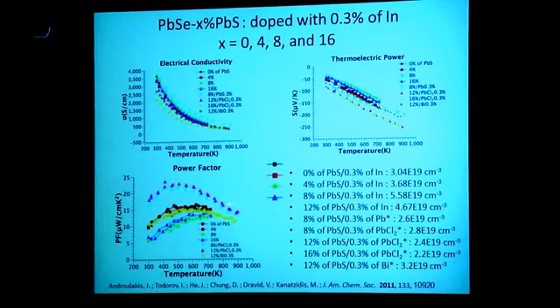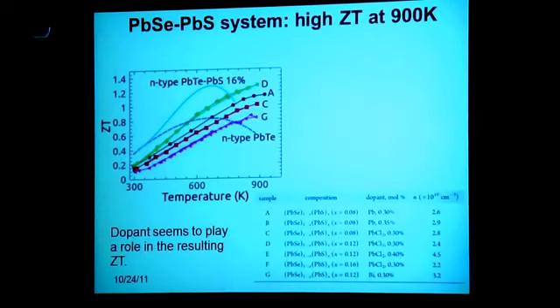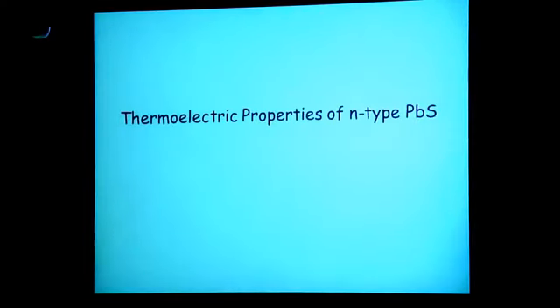By doing this optimization, you can get power factors that are very high, not as high as lead telluride, but nevertheless quite high for that. And then you can optimize the sample. And so here's an example. The sample D, the green data, has 12% lead sulfide. It's doped with lead chloride, and you get a ZT of about 1.3 at 900K. That is higher than regular N-type lead telluride, much higher, and almost as good as this nanostructured lead telluride, lead sulfide, only at a different temperature. So this is actually an exciting system because it's tellurium-free as well. And so our work continues with this.